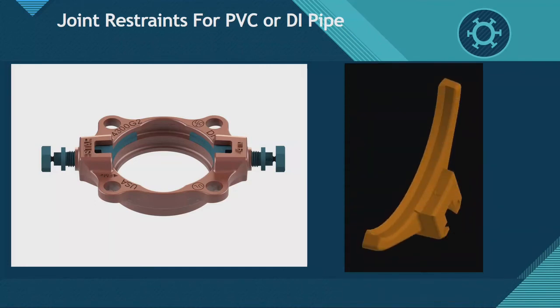You can see the wedges on this are long, similar to a PVC wedge, but the teeth on it are a lot more aggressive, more like a ductile iron wedge on it. So it will work on both. These are available just in 4 to 12 inch. It's great to keep in stores or something on the shelf, so if you have a break, you can bring out an 8-inch one that can be used on anything, and you know you're good to go if you're not sure what your pipe material is that you're going out to fix.